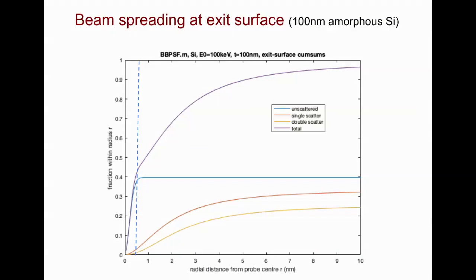But if we sum up the electrons that lie within a given radius, comparison of the blue and purple curves here shows that only 40% of the electrons lie within the original probe radius. The remaining 60% are distributed at distances up to at least 10 nanometers. This means that if we wanted to analyze a nanometer-sized precipitate that was located near the beam exit surface, 60% of our analytical signal would come from the surroundings, making quantitative analysis inaccurate.